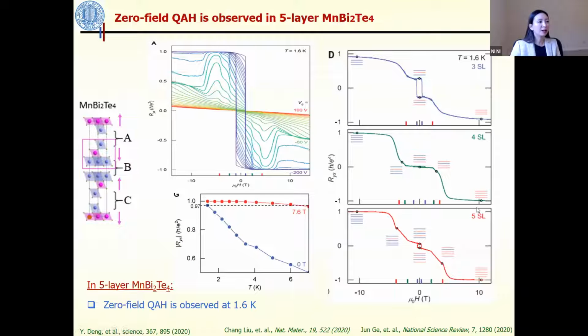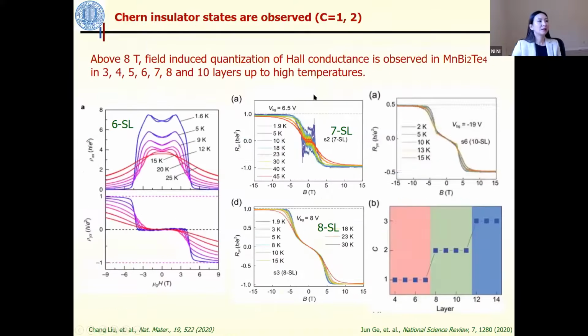Everybody worked really hard and the field moves really quick. Just half a year later, QAH was actually observed at zero field below 1.6 Kelvin in a 5-layer 1-2-4 device. This value, you can see, is orders larger than 30 millikelvin in the chromium-doped thin films, right? And later on, the quantized Hall conductance was also observed when the device enters into the forced ferromagnetic state under external fields. For example, you can see when it is 3-layer, 4-layer, 5-layer, 7, 8, and 10 layers.